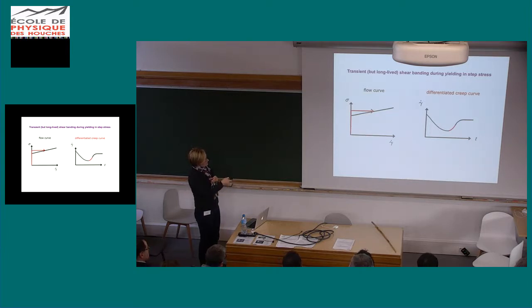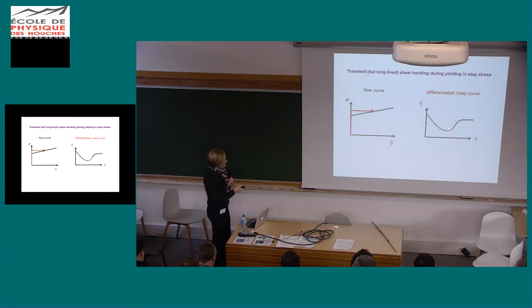Now, in the limit of long times, that has to get to the value on the ultimate flow curve. Typically, there's a region of sublinear creep here. This is sometimes called Andrade creep in the metals literature, where on this log-log plot, the strain rate is going down as a sublinear power in time, so the strain would go up as a sublinear power. The strain rate then undershoots, and that corresponds to the viscosity overshooting, and then one wakes up and starts to flow. So there's a yielding transition here.